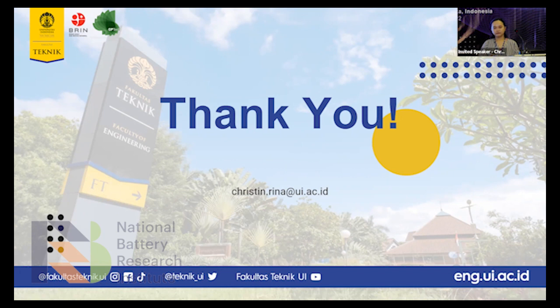The future of this battery will lead us to the solid state battery, and of course this solid electrolyte is an important thing that we need to improve. But the challenge we face is that the electrochemical performance is kind of poor. The ionic conductivity is below 10 power minus 6 or 10 power minus 5, but the industrial need is to improve it to 10 power minus 4. So I am curious why you chose PVA instead of other polymer hosts such as PEO, because they have a record that can lead us to higher ionic conductivity. And if you still want to use PVA, is there any chance to increase the ionic conductivity numbers again? Thank you.